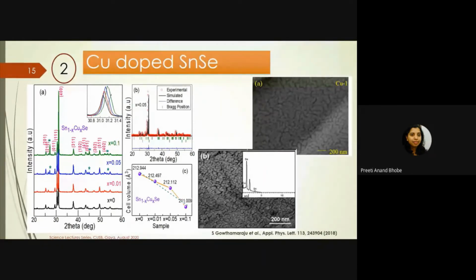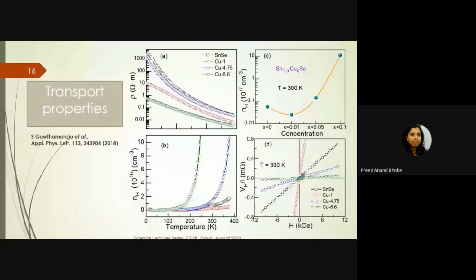But what we realized is that when we study this material, what happens to the transport properties, the electrical conductivity of it? Obviously, if you are putting copper, then you expect that the electrical conductivity will improve or resistivity will come down. And that's what we see here. The black curve is that of SnSe in this figure, where resistivity is plotted as a function of temperature. And as you put in copper, you slowly start decreasing the electrical resistivity. So that aim is achieved: if you put copper in SnSe, we have a better electrical conductivity. And that is what we see here.